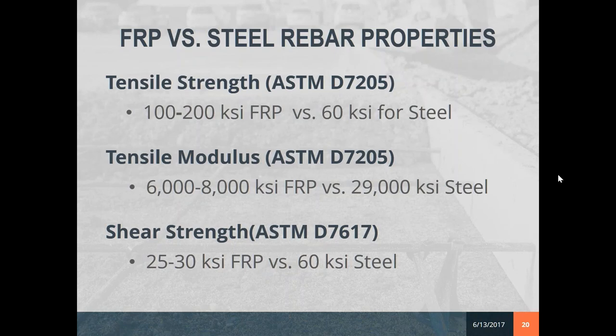Tensile strength, this is one of the beauties and advantages of FRPs. You get a much higher tensile strength. Generally, they range from about 100 to 200 KSI. With steel, we generally use around a 60 KSI steel in most of our designs. Another property of FRPs is the tensile modulus, or modulus of elasticity. It is lower than steel. It's not as stiff, so you just have to understand the material that you deal with.